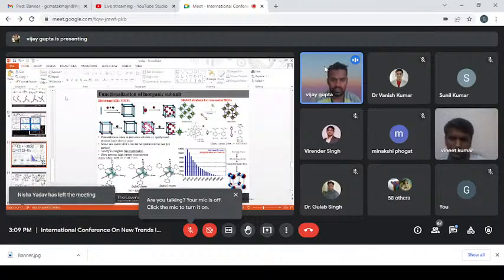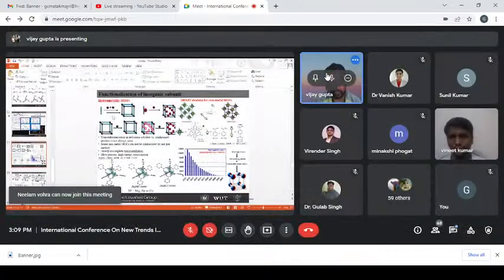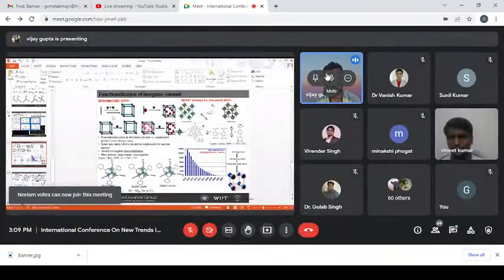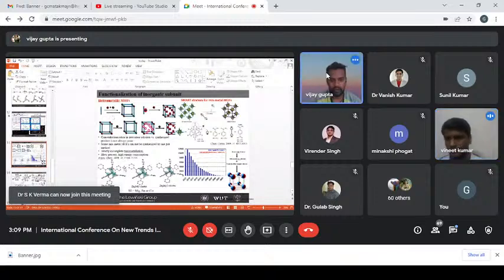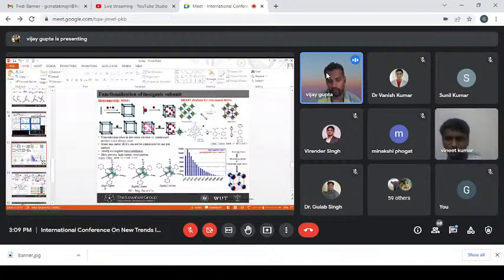there are only 4 strategies to make these mixed metal MOFs or heterometallic MOFs. Either you use 2 metals, but there is no possibility that whatever starting ratio you use, that will go into the end product. So what we try to do here is make some heterometallic building blocks. Instead of the zinc 4 oxo benzoate cluster, as I showed you, we synthesize some zinc 3 M oxo clusters, zinc 2 M2 oxo clusters, and this kind of clusters.